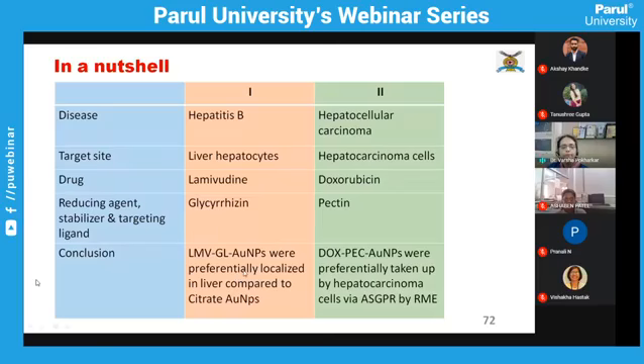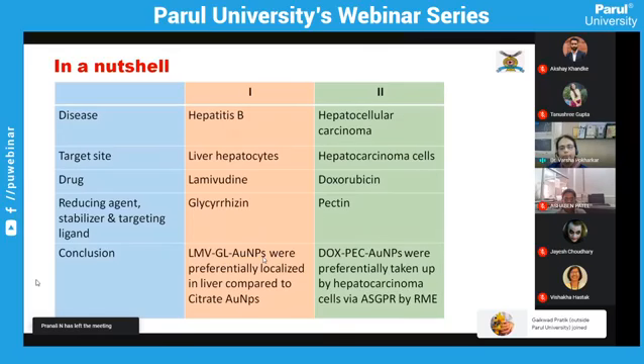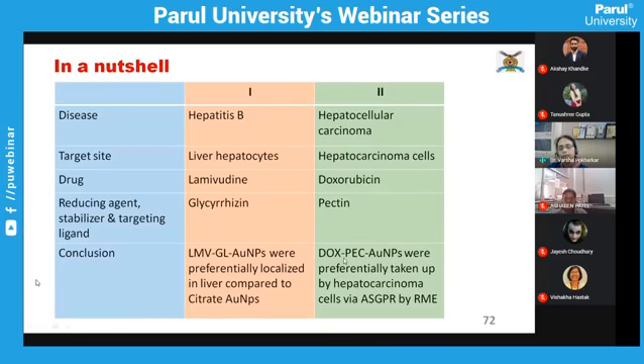In the first study, we could successfully demonstrate that the lamivudine loaded glycyrrhizin reduced gold nanoparticles were preferentially localized in liver compared to the citrate reduced gold nanoparticles. And in the second case study, we could demonstrate that the DOX loaded pectin gold nanoparticles were preferentially taken up by the hepatocarcinoma cell via the asialoglycoprotein receptor, by receptor mediated endocytosis.